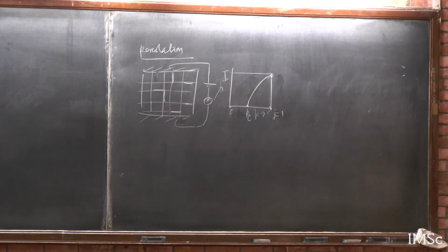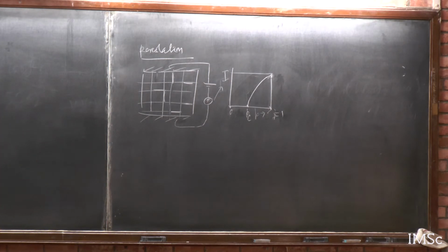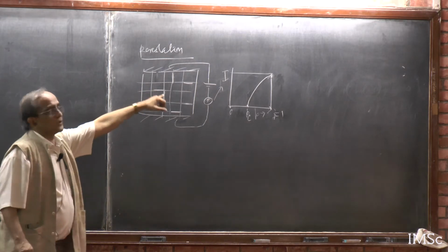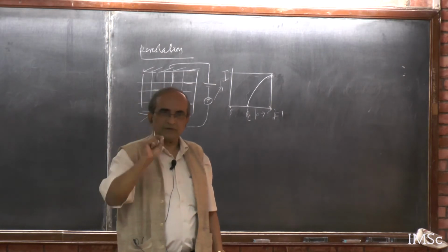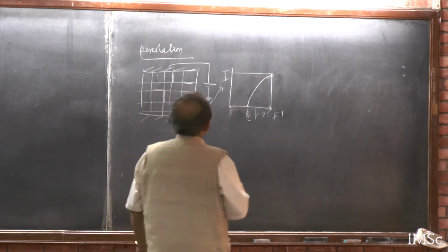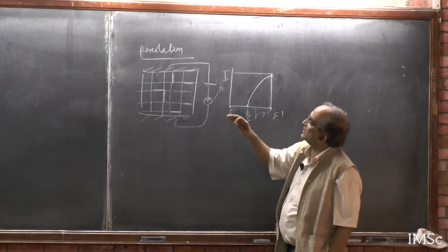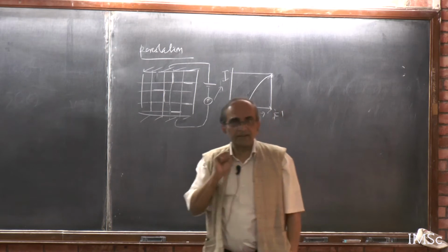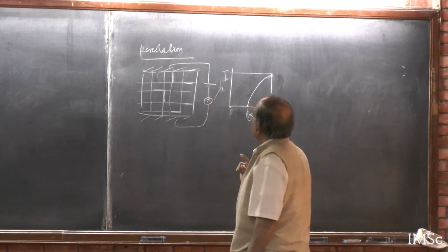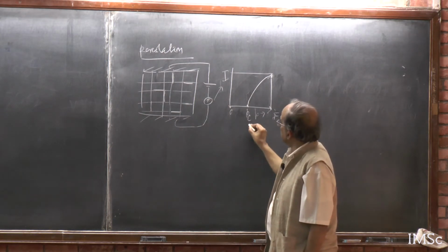But here one order parameter may be very simply defined. I did it in a bond way, one could do it in a site way. The sites were randomly occupied with probability p or not p. By the way, this point is not universal in the sense that it depends on whether it is a square lattice or a triangular lattice, whether you are throwing bonds or sites. For example, on a square lattice, bond p_c is half.